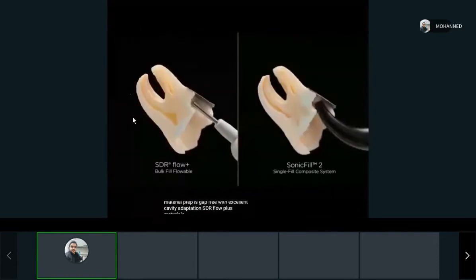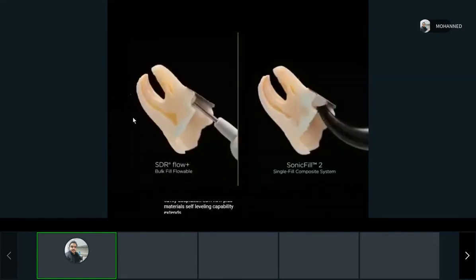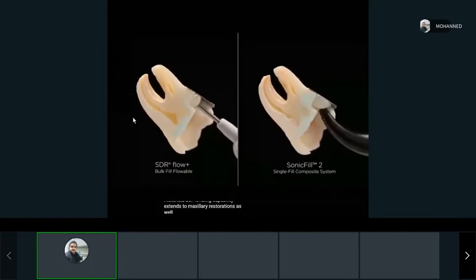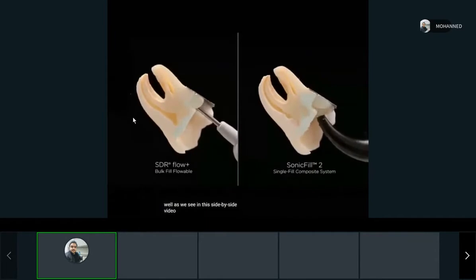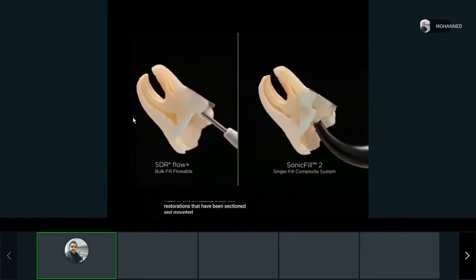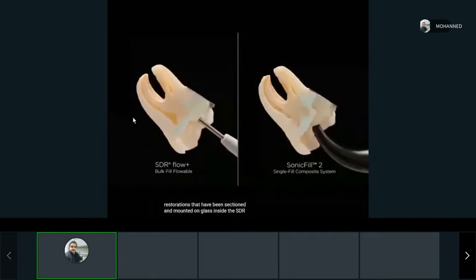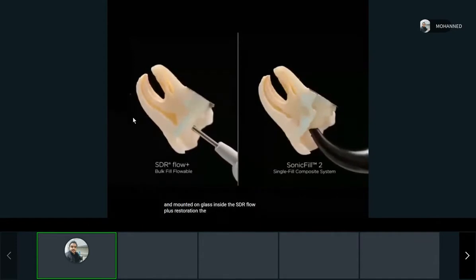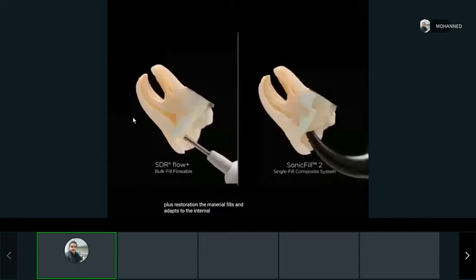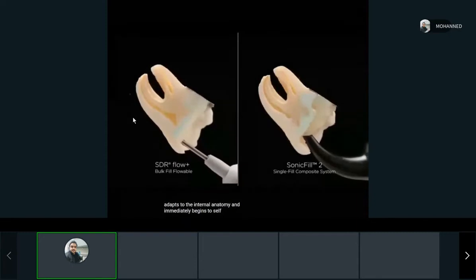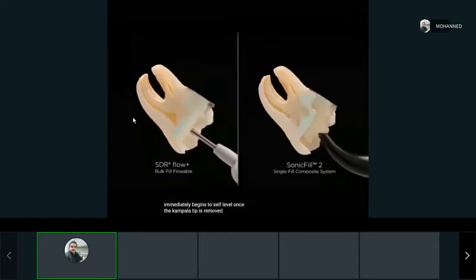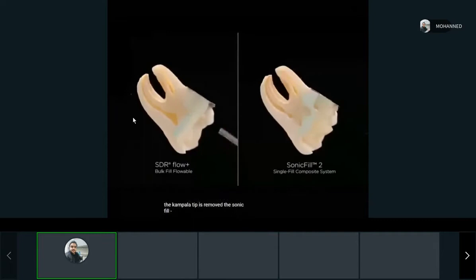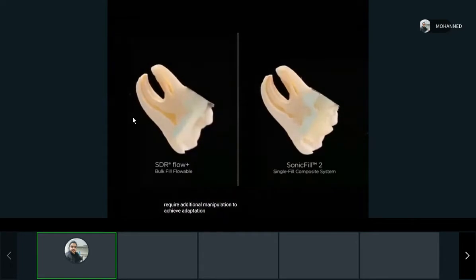SDR Flow Plus material's self-leveling capability extends to maxillary restorations as well, as we see in this side-by-side video of two simulated Class 2 restorations that have been sectioned and mounted on glass. Inside the SDR Flow Plus restoration, the material fills and adapts to the internal anatomy and immediately begins to self-level once the compule tip is removed. The Sonic Fill 2 restoration does not, and would require additional manipulation to achieve adaptation.